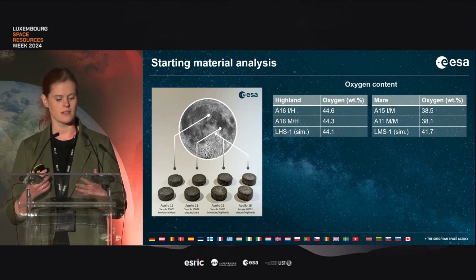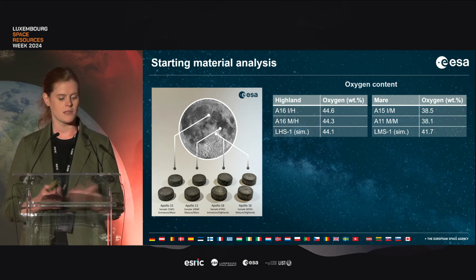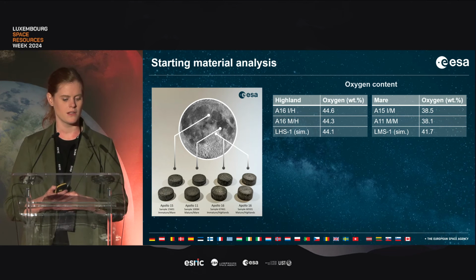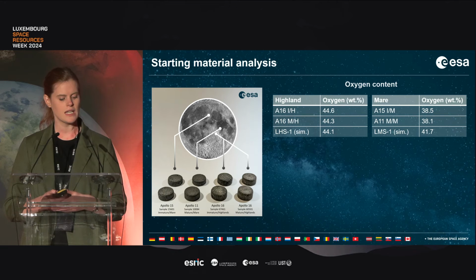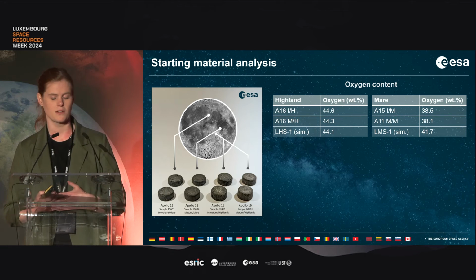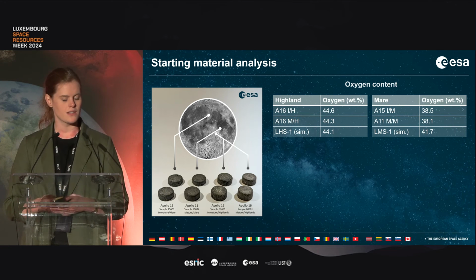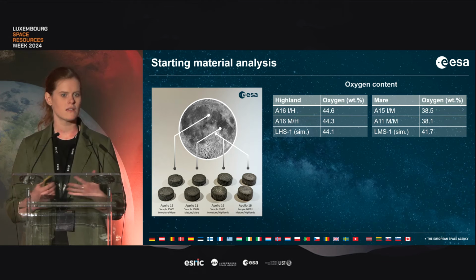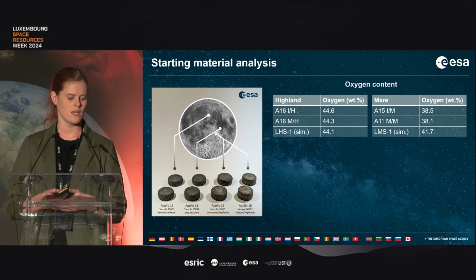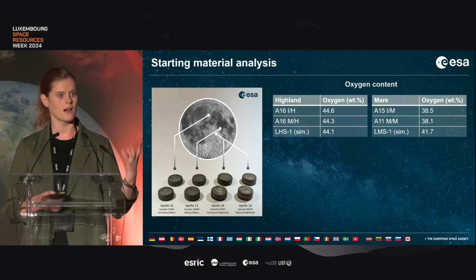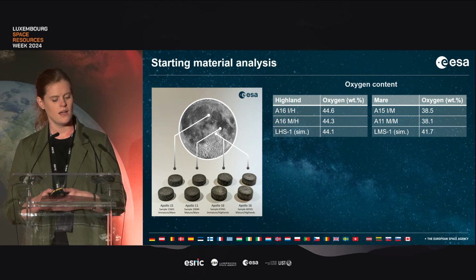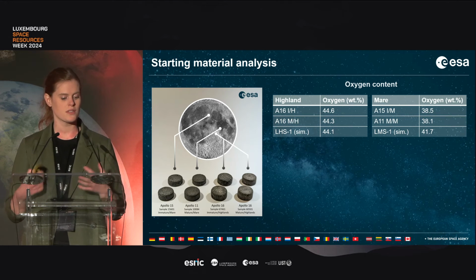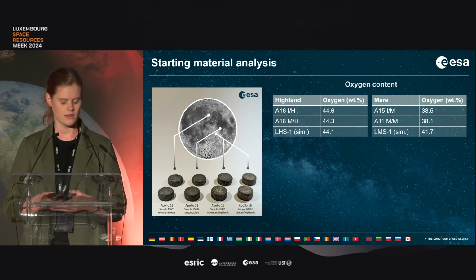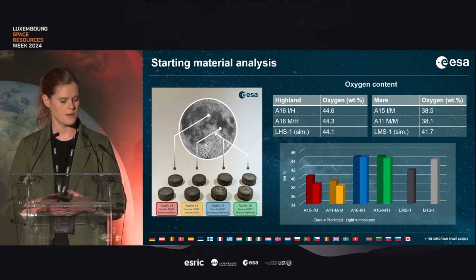However, for the Mare material, we got quite a different result. It's about 10% less oxygen available in that material. The Apollo 15 and Apollo 11 both had around 38% weight oxygen, compared to the Mare simulant material that had closer to 42%. And so this is kind of reflective of the really unique environment on the lunar surface, where material that has a really high iron content, like the Mare material, is going to be in a much more reduced state because of that micrometeoroid bombardment, so with that nanophase iron being present.